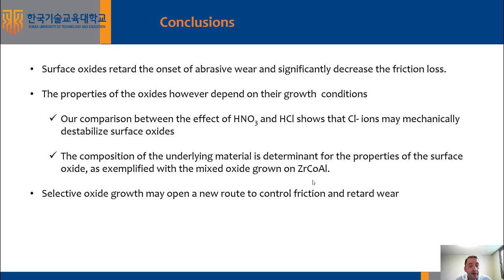Also, the composition of the underlying material is determinant for the properties of the surface oxide, as shown ultimately on the zirconium cobalt aluminum sample. Last, I would like to state that selective oxide growth may open a new route to control friction and to retard wear.